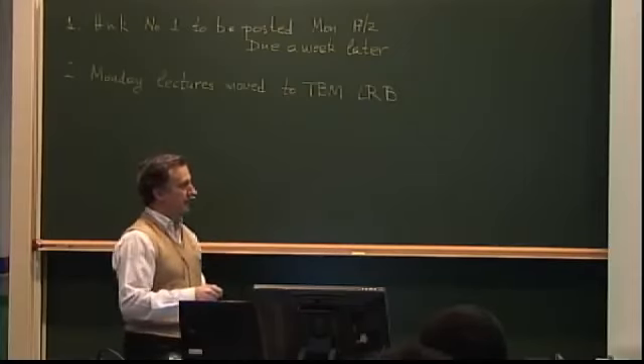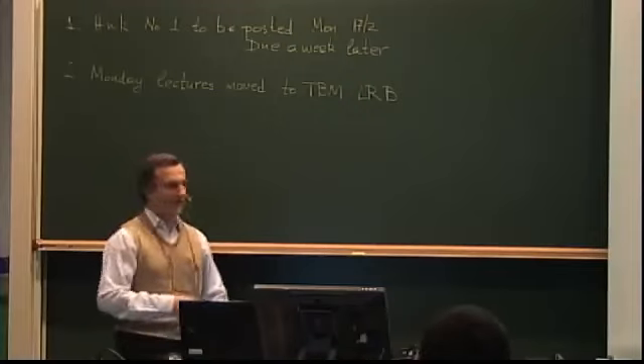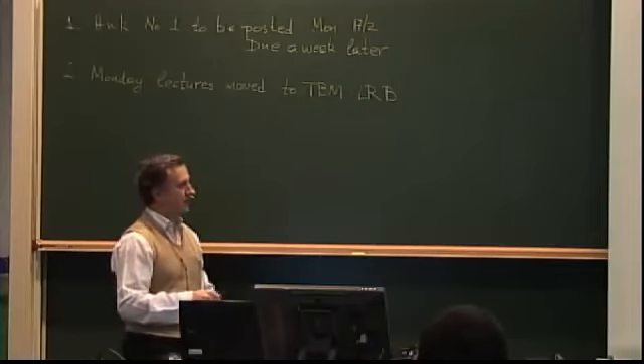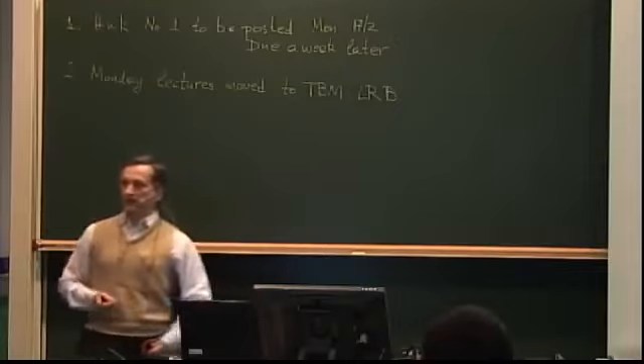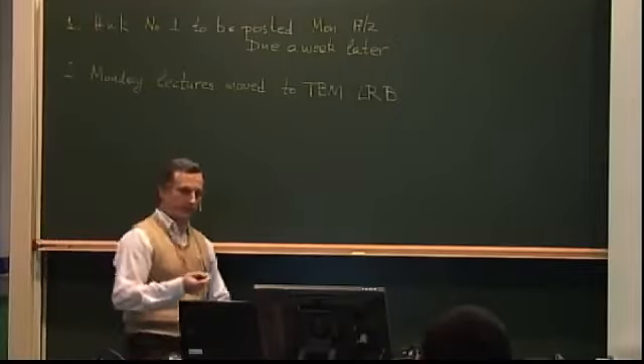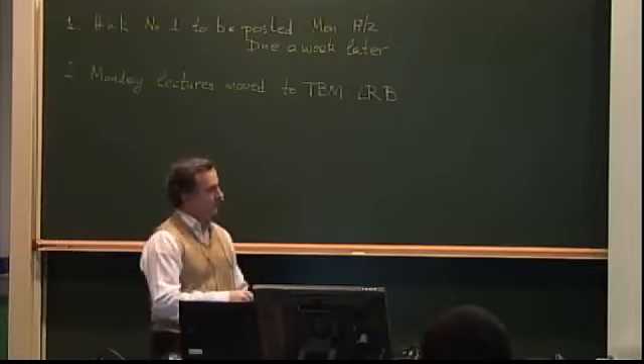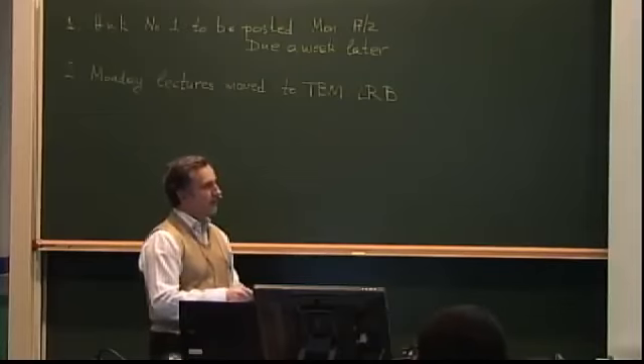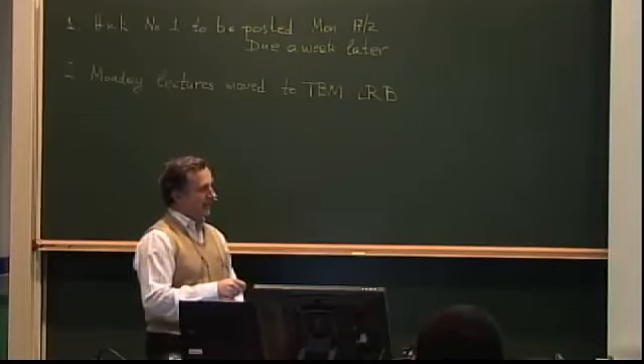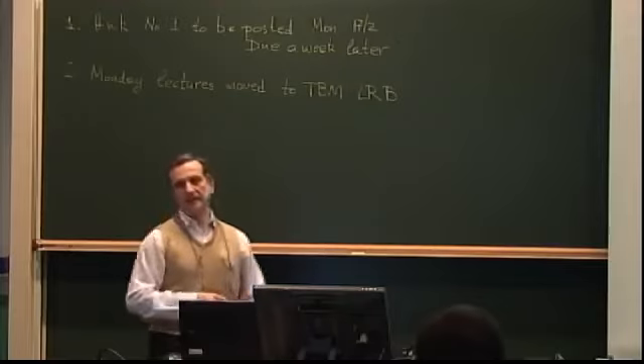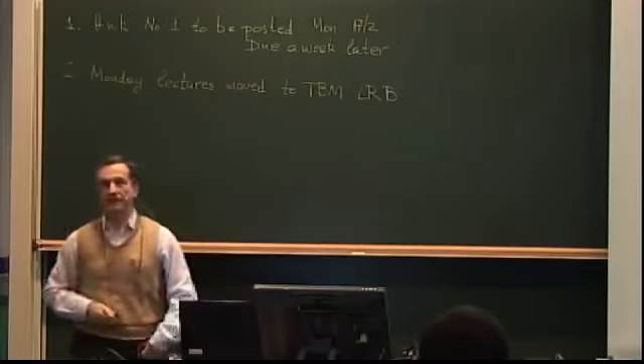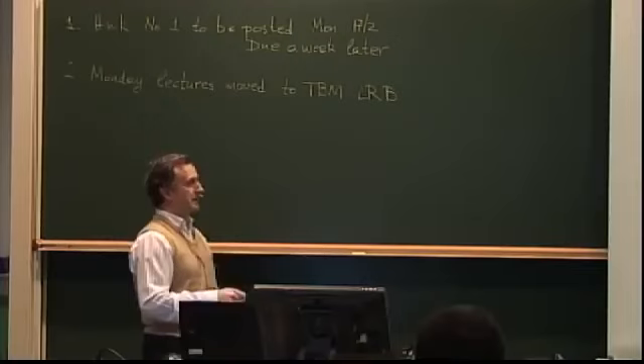If I have an applied force, I get, in general, three strains in my laminate. If I have an applied strain, or three strains applied, I end up with in-plane forces. One important characteristic for a composite, notice the presence of this term. Basically, I can apply an axial force and get a shear strain, or I can apply a shear strain and get an axial force.